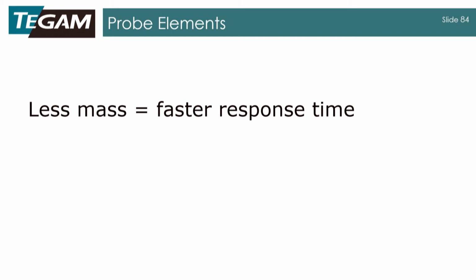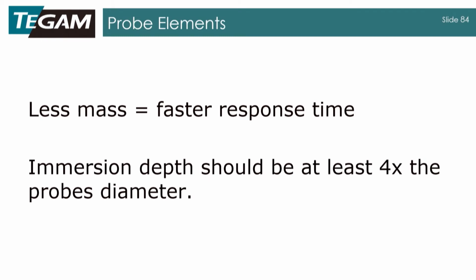All right, so the main things to glean from that was with the less mass, we had a faster response time. And I don't know if you could tell, but I was being very careful to make sure that the immersion depth was at least 4 times the probe diameter on the one with the sheath.